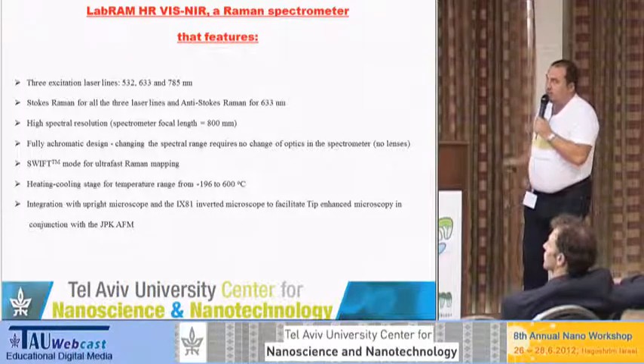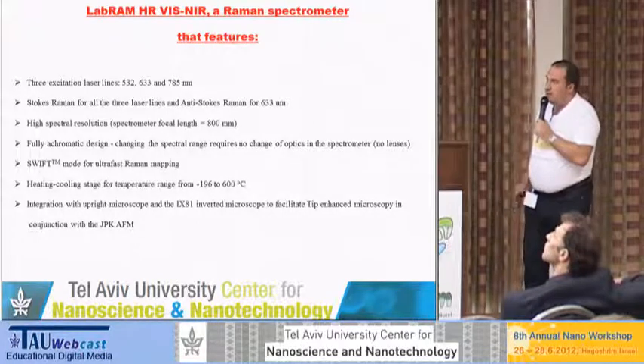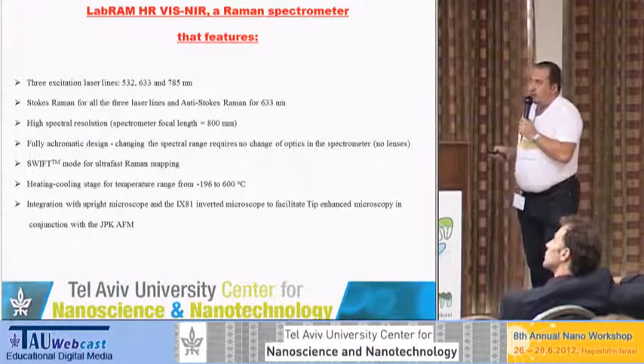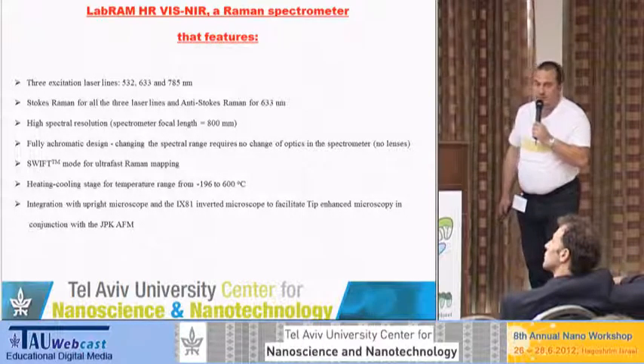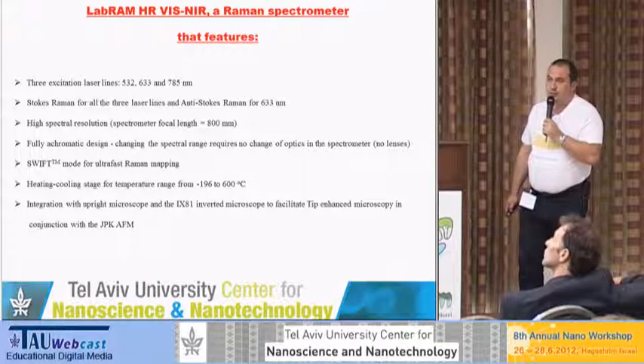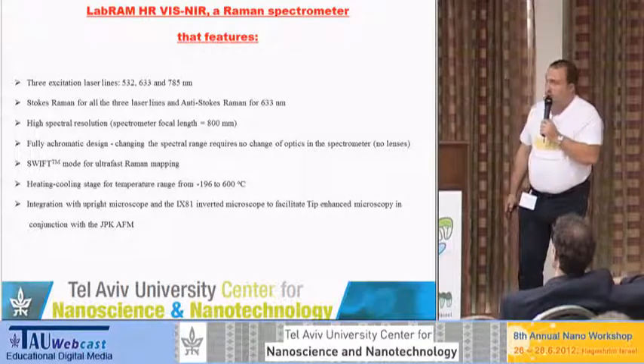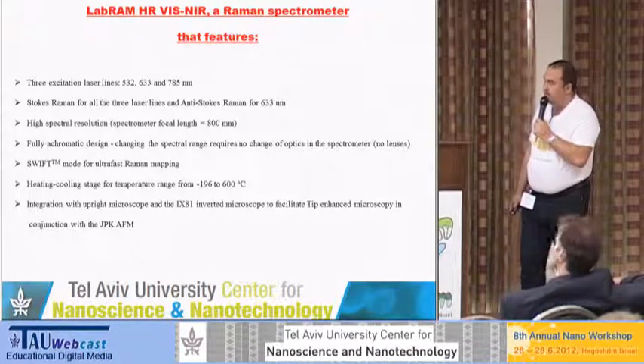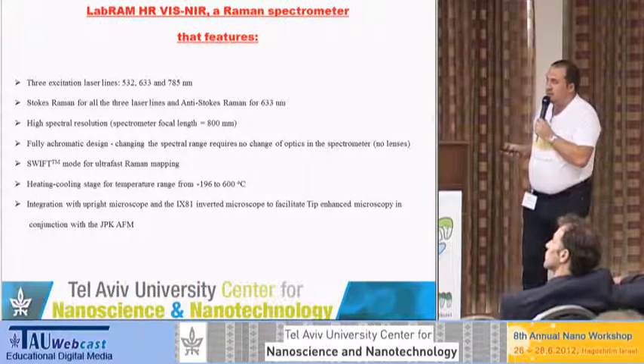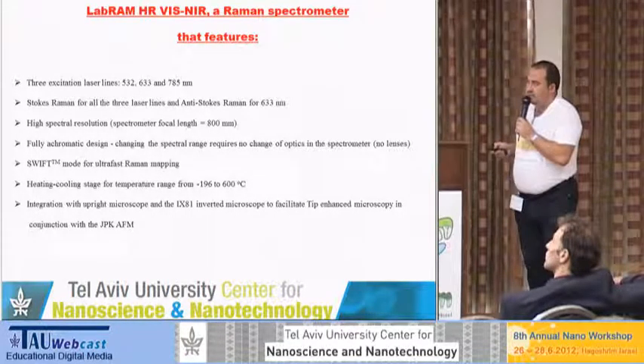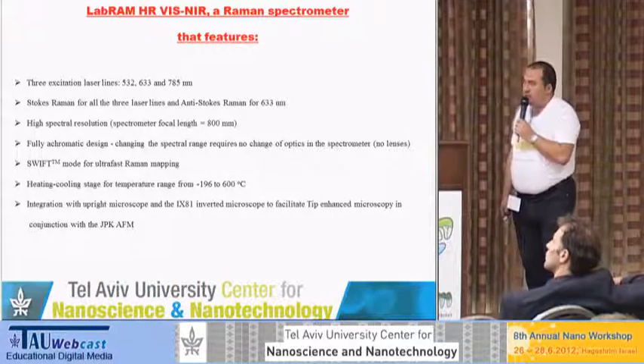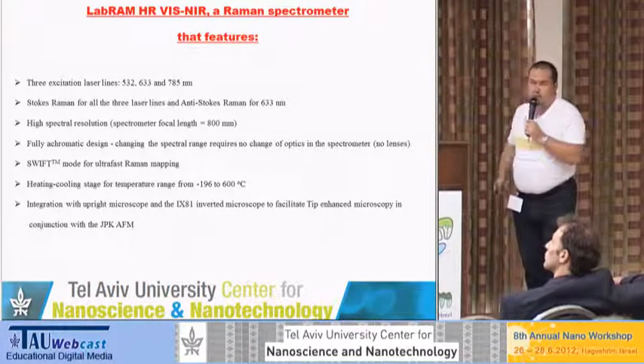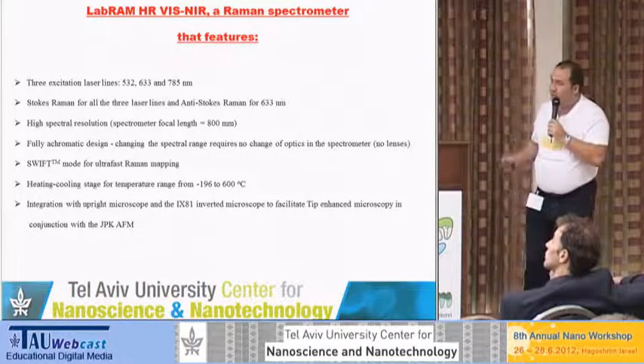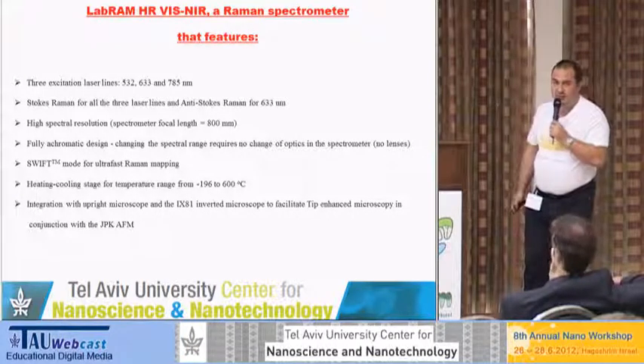The Raman system has 3 lasers, 532, 633, and 785. It is capable of taking Stokes and anti-Stokes Raman scattering, anti-Stokes for the 633 line. It has quite good resolution because of the focal length of its spectrometer. The resolution can get up to 0.3 cm^-1. Achromatic design, mapping option, also fast mapping option, and it also has a heating cooling stage working from the liquid nitrogen temperature up to 600 degrees centigrade.